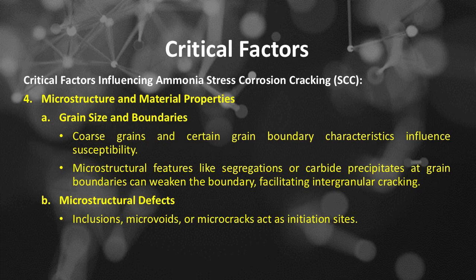Critical factors. Number 4 is microstructure and material properties, includes, number A, grain size and boundaries. Coarse grains and certain grain boundary characteristics influence susceptibility. Microstructural features like segregations or carbide precipitates at grain boundaries can weaken the boundary, facilitating intergranular cracking.